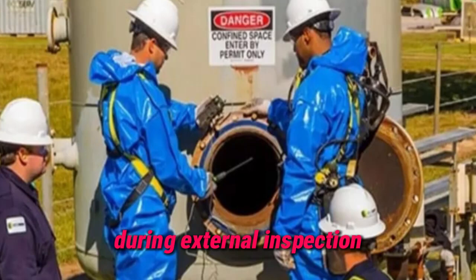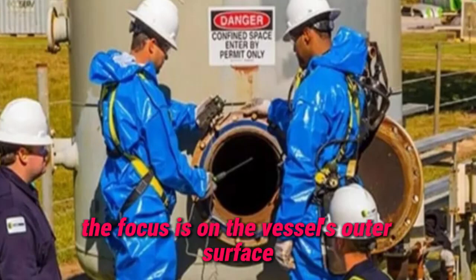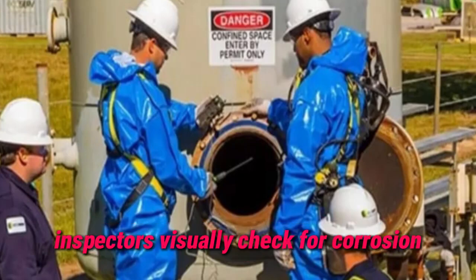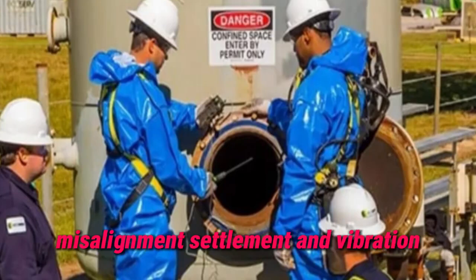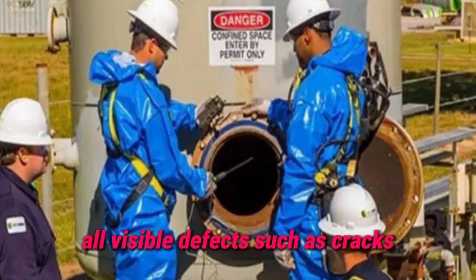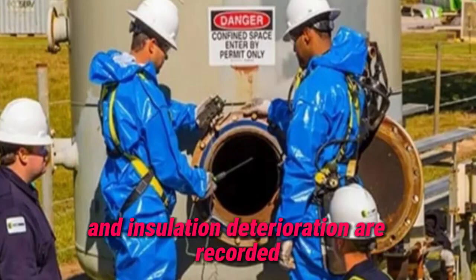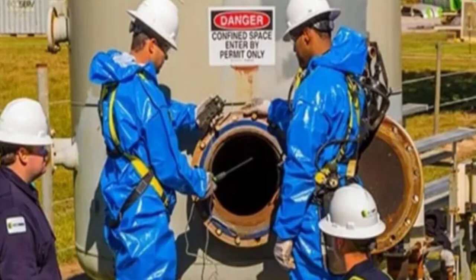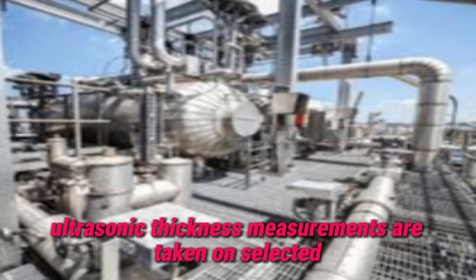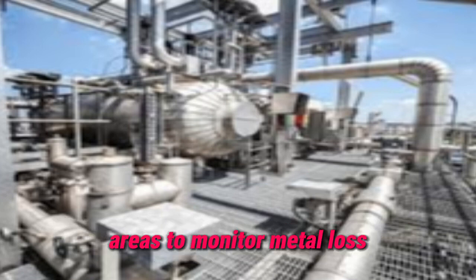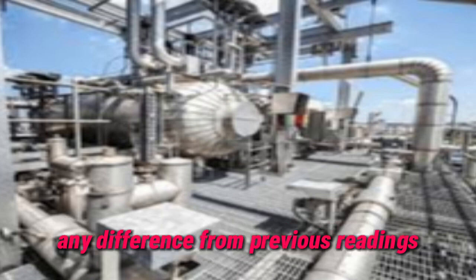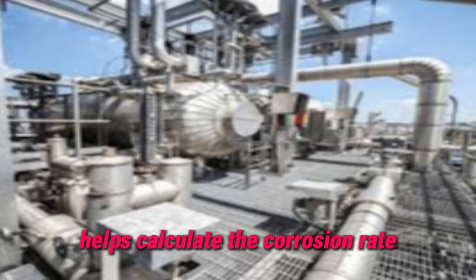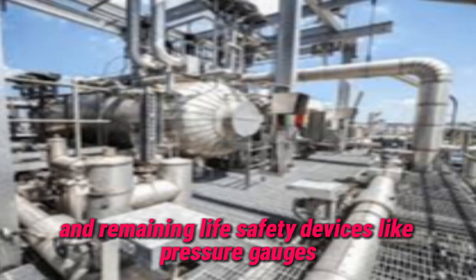During external inspection, the focus is on the vessel's outer surface and attached components. Inspectors visually check for corrosion, paint deterioration, leakage, misalignment, settlement, and vibration. All visible defects such as cracks, coating damage, and insulation deterioration are recorded. Ultrasonic thickness measurements are taken on selected areas to monitor metal loss over time. Any difference from previous readings helps calculate the corrosion rate and remaining life.